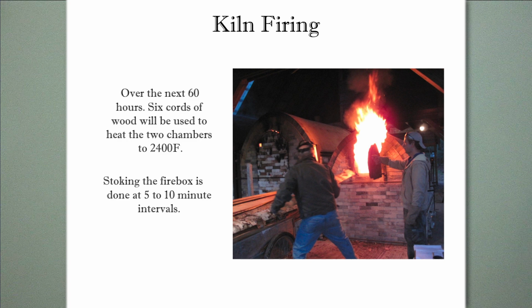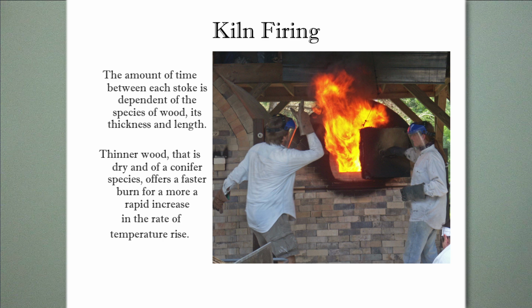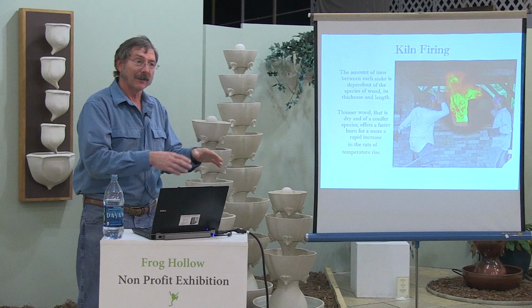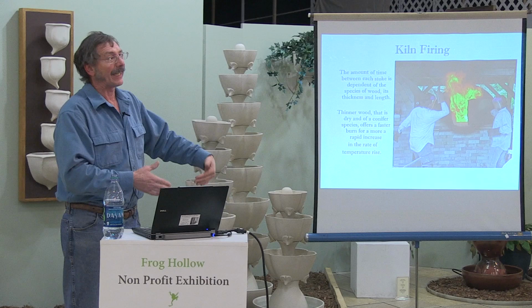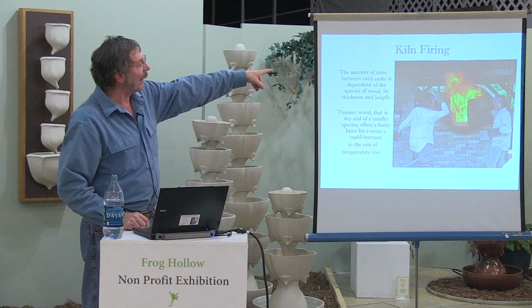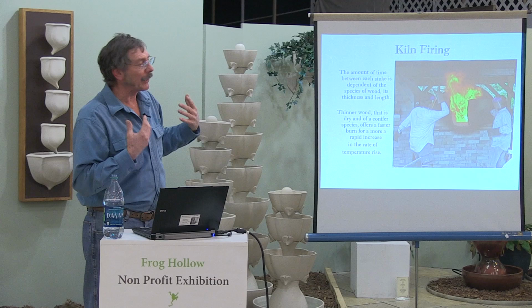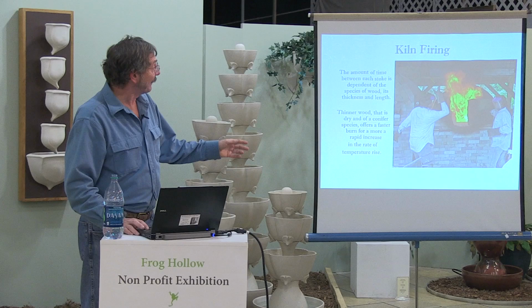And again, my firebox door is very high, not because it needs to be, in fact, it shouldn't be. It should be lower in order to drive the fire into the next chamber. But I didn't want to bend over. And I didn't have the ability to step down the ground the way I mentioned Bruce Martin had done in New Zealand, which would have been a great idea. I actually thought about jackhammering the concrete and building down, but that idea didn't last too long. So I built my firebox about 3 foot higher than it needed to be. When you open a firebox door, you tend to get this back pressure at first. It only lasts for about 10 seconds, but it's quite a treat when it happens.